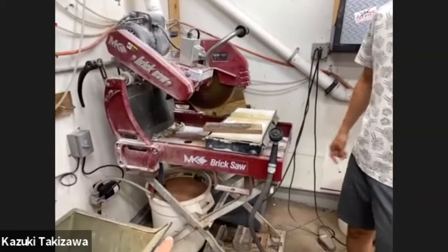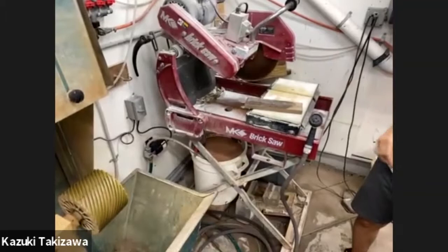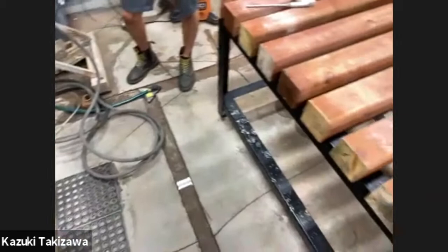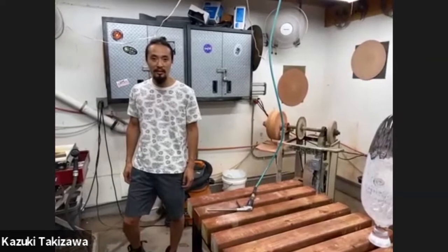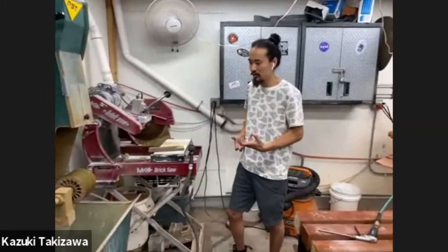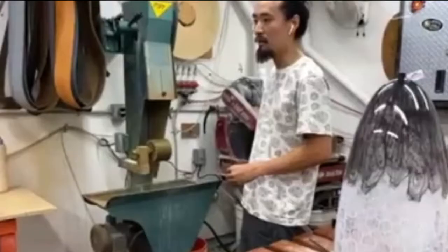And I see water. Yes. The water is there any time we do cutting or grinding or polishing, because the rotation of the tool is going to heat up the glass really fast. And then, when the glass heats up, it cracks. So usually we're in here very slippery, and you've got to hold on to your piece. That's one thing that's a little bit different between the hot shop and the cold shop: we actually use water and these abrasive wheels and saw blades to shape the glass.